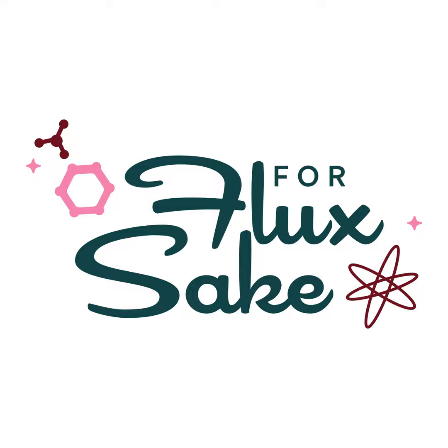Like I was writing glaze recipes last week and I had a set, they didn't have any kaolin in them. So just like 2% across the board. You don't need to adjust it. You don't need to compensate for its chemistry for the hardcore nerds out there. The contributions of silica and alumina are so small. It really is basically not even worth noting, and you need it for the suspension anyway. So, you know, just 2% should keep it, but put it in the dry mix, not in the wet. Excellent. Words to live by.